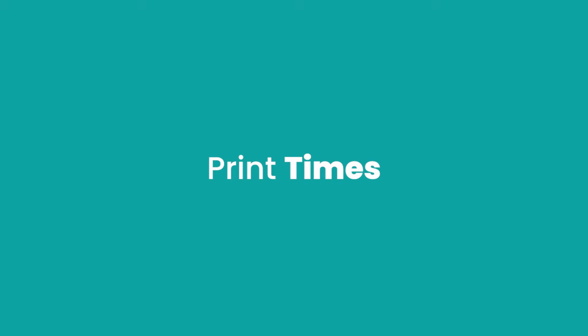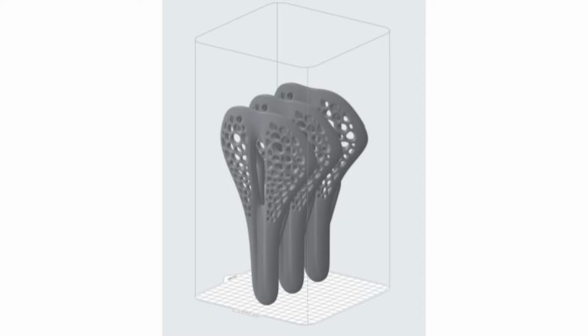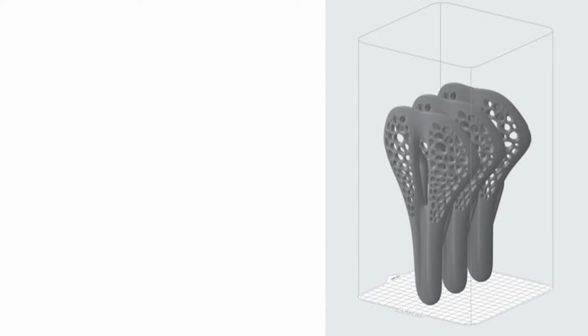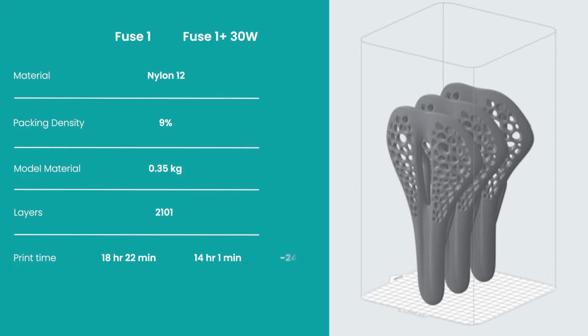So let's have a look at print times with some examples. Here we have a comparison between the Fuse1 and the Fuse1 30W. If we were to print these three saddles, the packing density is 9%. With the Fuse1, you can print it in 18 hours, 22 minutes. With the Fuse1 30W, you can print it in 14 hours. The print time improves by 24%, and this is thanks to the improvement in speed in the Fuse1 30W.